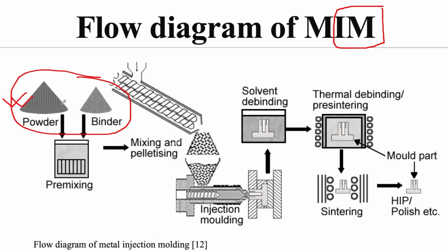Now, what happens? This powder is mixed with some kind of plastic and some other additives, and this is fed to the injection molding machine. What happens in the injection molding machine when the temperature is supplied? This powder does not melt, but the thermoplastic elastomer or the binder, which are polymer-based materials, melt, become semi-solid, and when they are pushed into the cavity, they take the shape of the cavity.